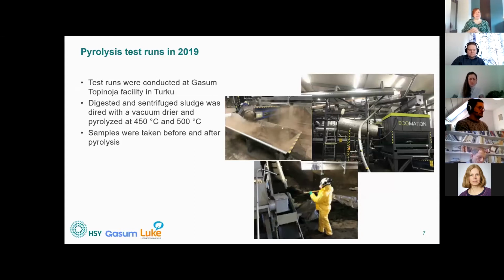So in 2019 we did some pyrolysis test runs at the Gasum facility. At that point they owned a small, sort of pilot scale pyrolysis facility in Turku. And so we tried our sludge and their sludge. There's a bit of difference between the sludges. And we dried them. There was a vacuum dryer, and we pyrolyzed them at 2 different temperatures to see if there's any differences between the temperatures. And we took samples before and after pyrolysis. So we had samples of dried sludge and then the pyrolyzed sludge that we call SludgeChar.